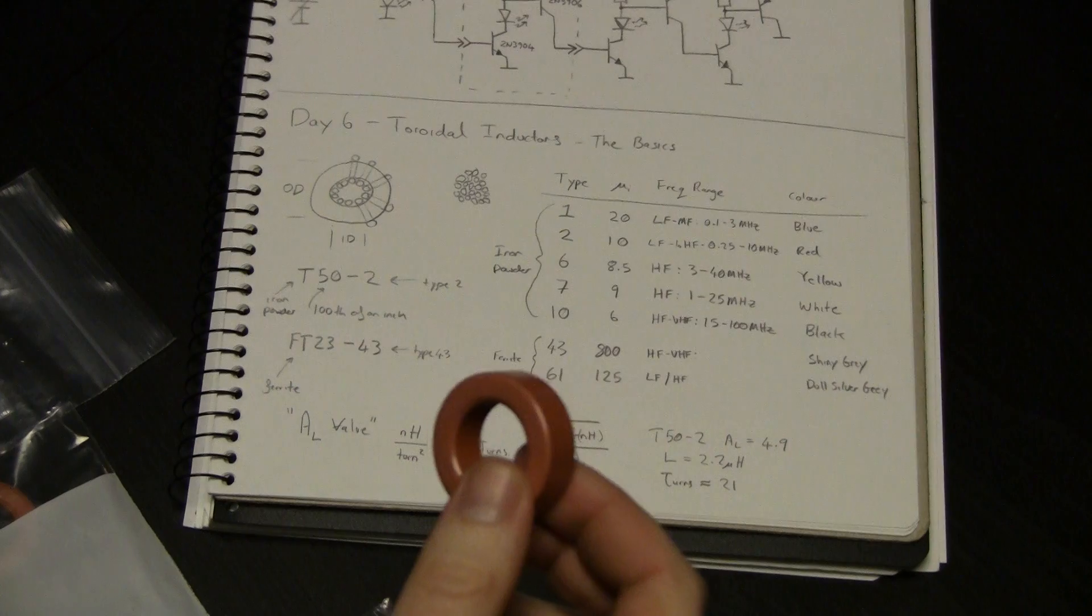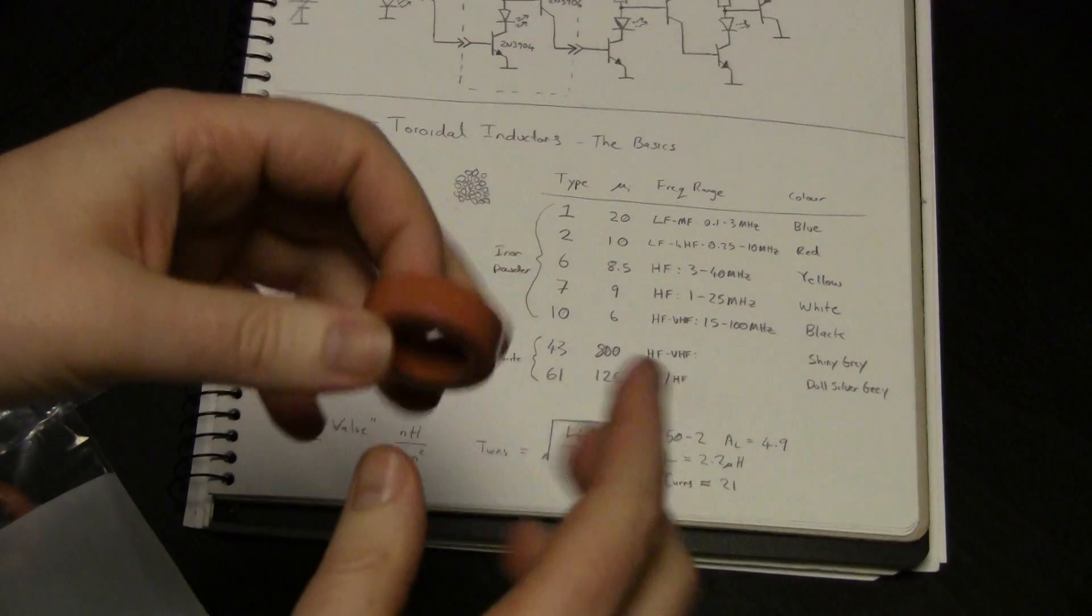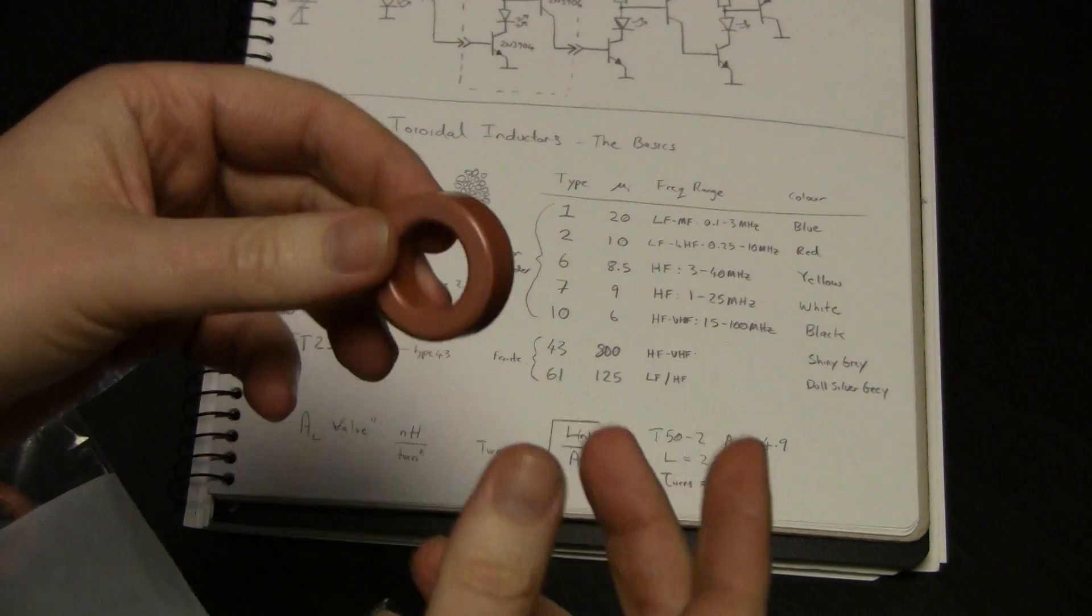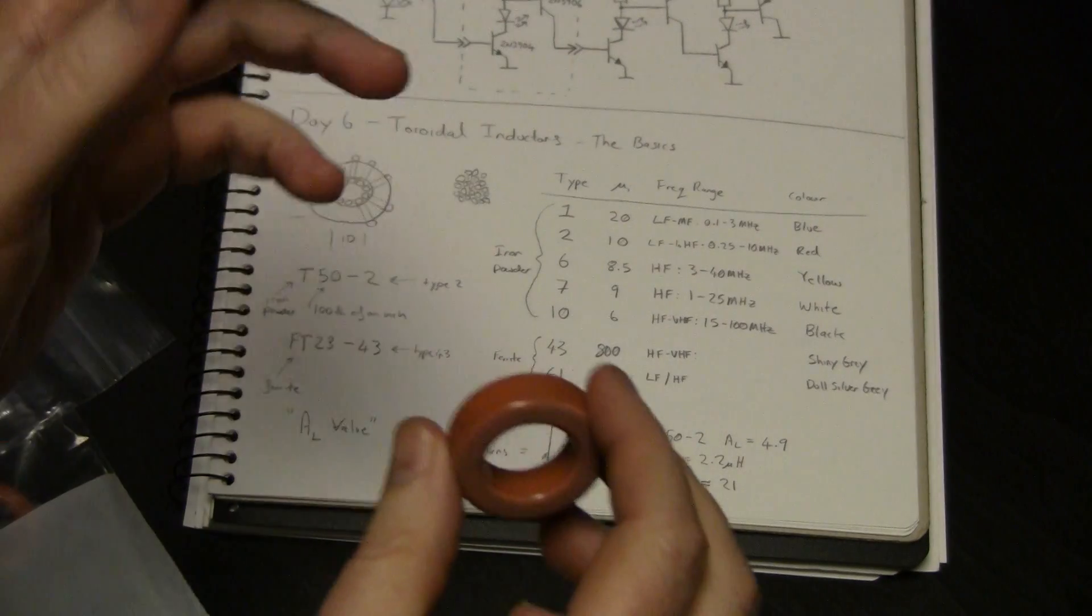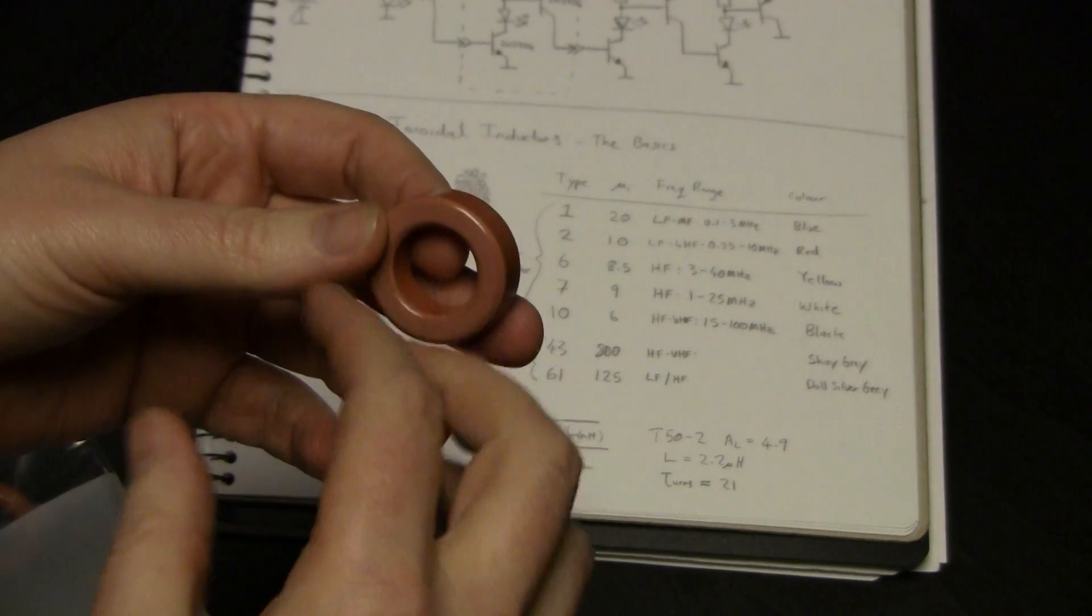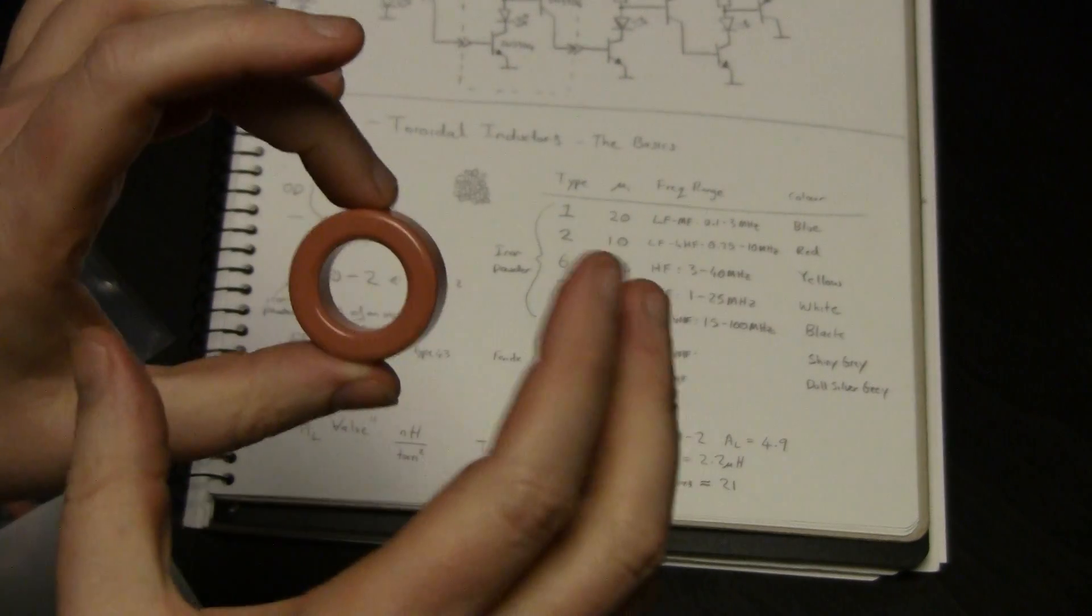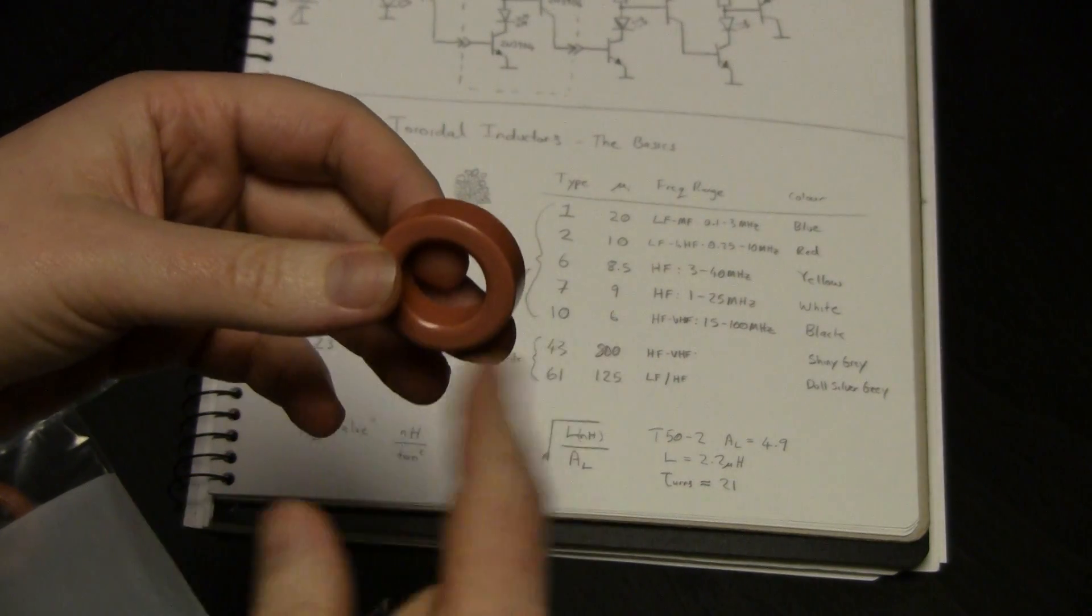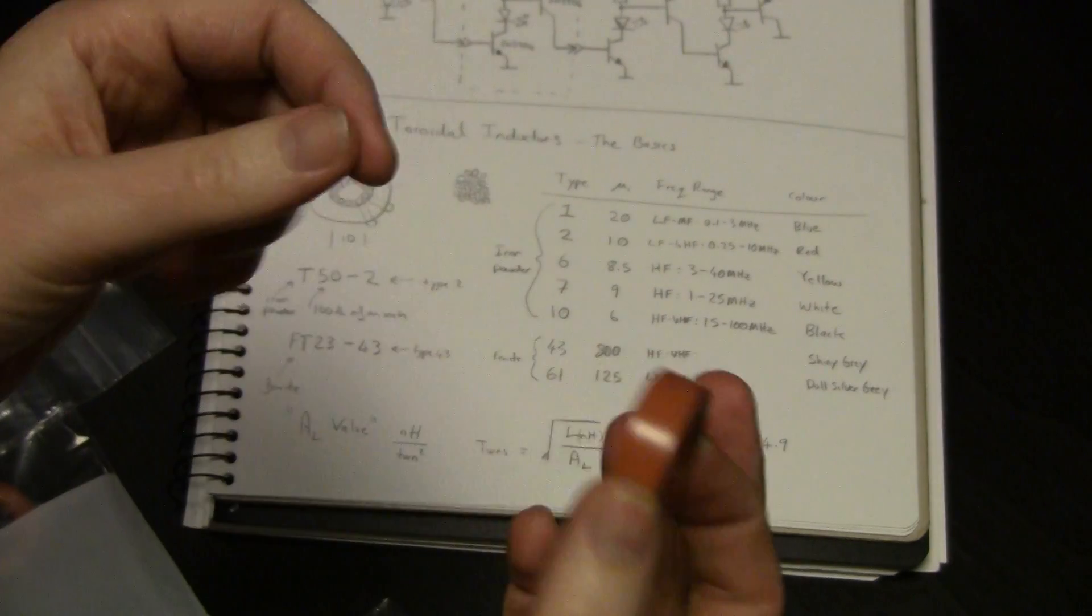We won't talk too much about that. It has to do with saturation, and we'll talk about that possibly in a later video because it's a really interesting topic, particularly in terms of power conversion, switch mode power supplies and flyback power supplies. For iron powder, the important thing to know is that distributed gap, because every particle has a gap between it and the corresponding particle next to it, means that there's a very soft saturation. So as the magnetic field increases, the induction in the core increases. Eventually the material can no longer be polarized anymore and it stops contributing to the increased relative permeability of the core material. When that happens, the material saturates out and it can no longer help you, so the inductance of the coil drops. It drops quite dramatically, essentially back to the vacuum inductance of the winding, as if it just had air or vacuum in the core.